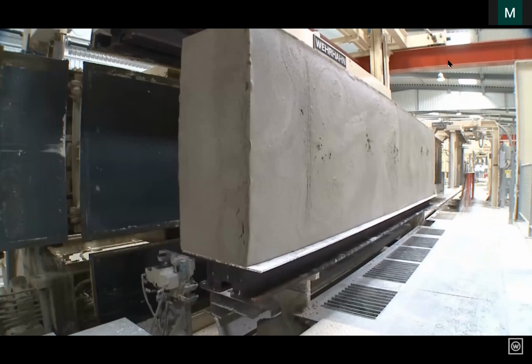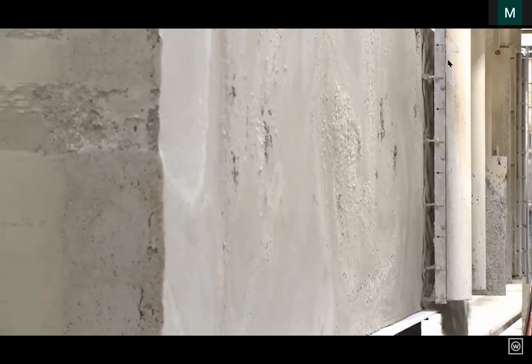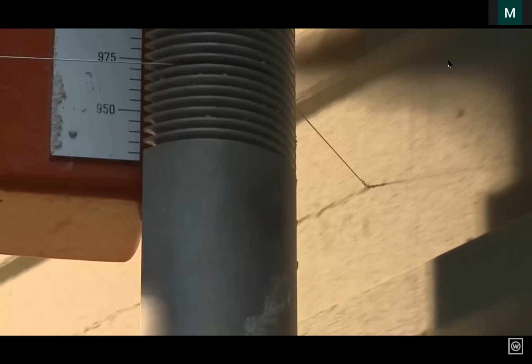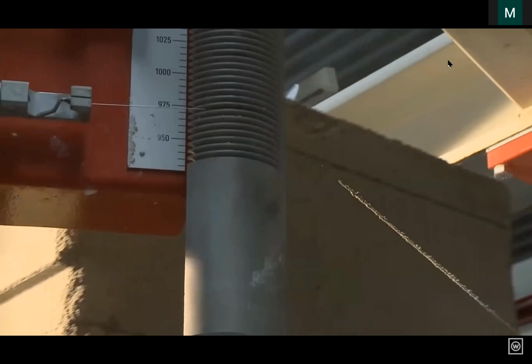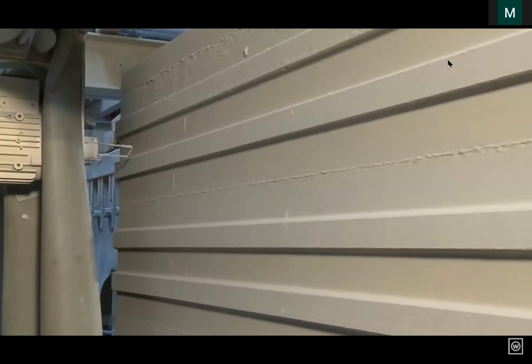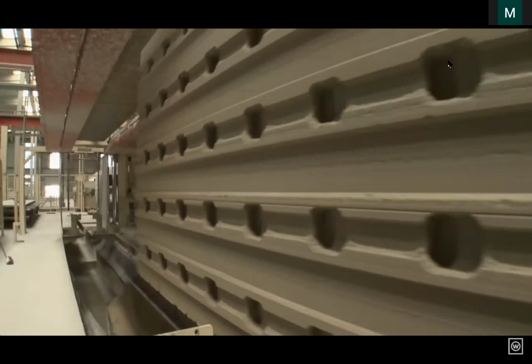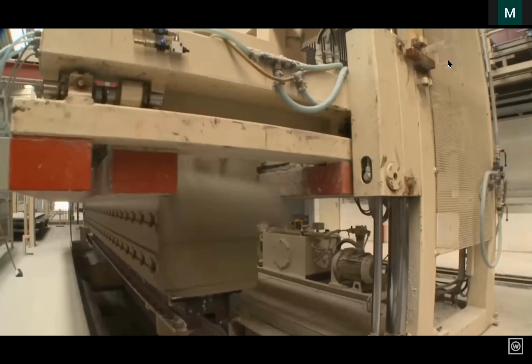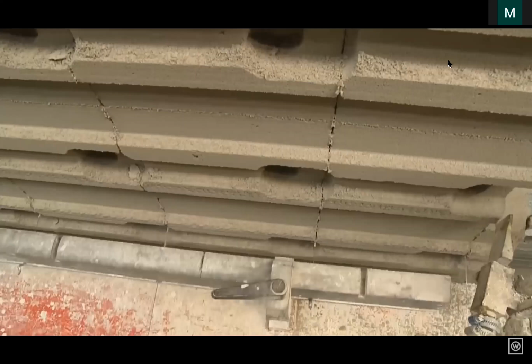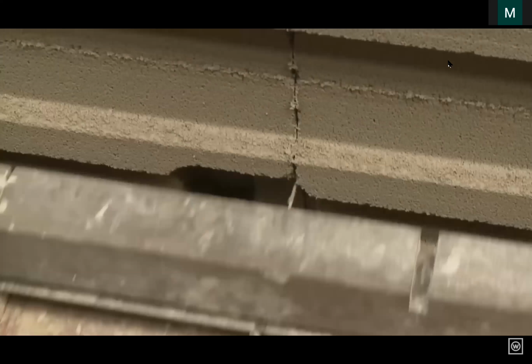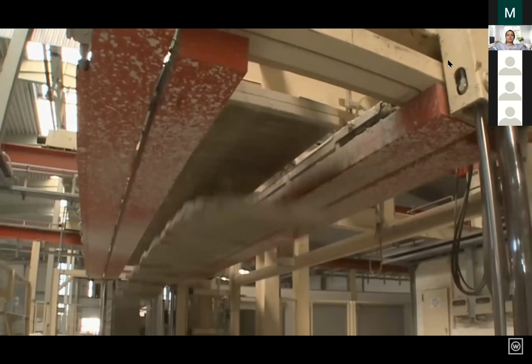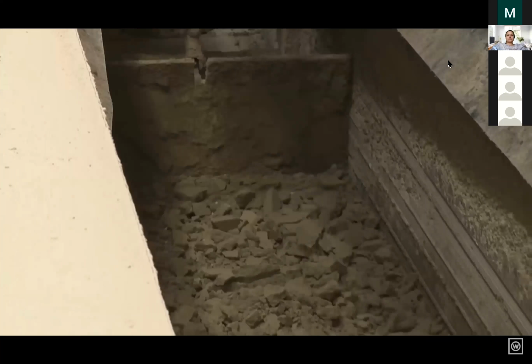First, the block length is cut in the side trimmer and tongue and groove are profiled when applicable. In the second step, the block or panel thickness is cut. Handholds are either cut in an individual machine or integrated in the cross cutter. In the final step, the cross cutter cuts the block height or the panel length. Shortest possible wires are used to facilitate high cutting accuracy. Wehrhahn's no-waste system saves 4-5% raw materials in comparison to other tilt-cutting systems.